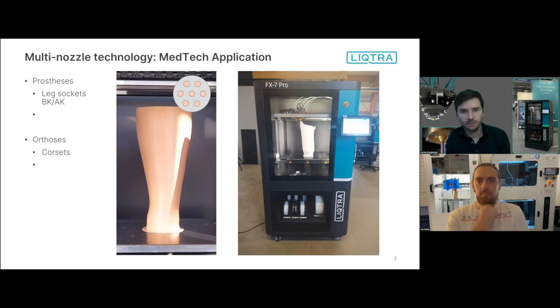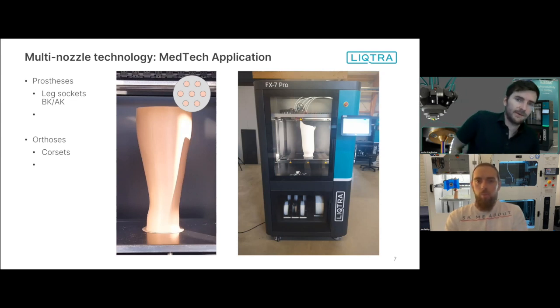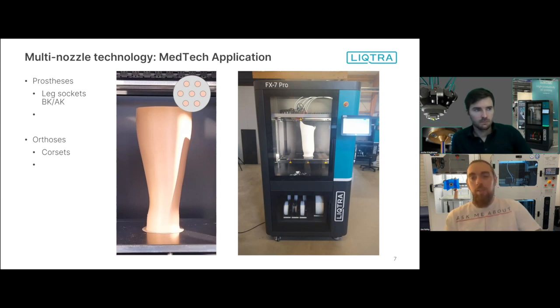Here in the US, polypropylene is looked at as somewhat of a preparatory-phase material for getting an amputee up and walking for a short period — maybe up to just one year. We do print quite a few preparatory prosthetic sockets that way, although they certainly are definitive in nature, being able to withstand forces over one year of use. We've shown that through cyclic testing of over a million cycles for our solid ankle and articulated AFOs printed in polypropylene. A lot of that application is also in the orthotics side. For prosthetic sockets I like polypropylene because it's lighter weight. I have some pretty cool colors from PP Print — I'm about to do a print for an above-knee prosthetic socket in PP Print's blue polypropylene. I would try to use a one-millimeter nozzle to decrease print time, but even then, a similar socket would take 24 to 48 hours.